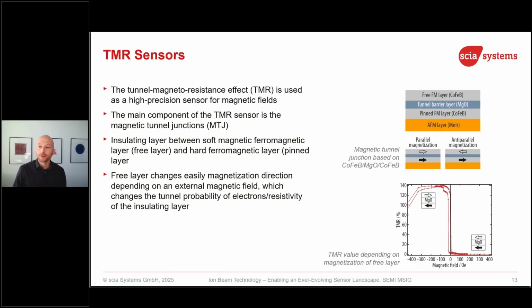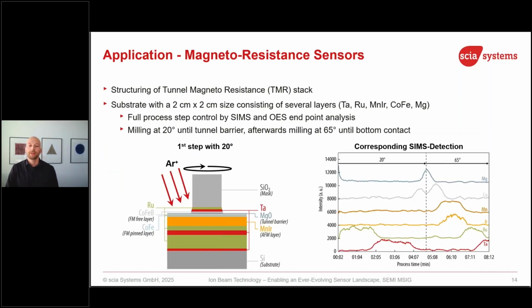So we have a lot of different materials. We have this oxide layer, we have magnetic materials, and even more. Now we have to make such a sensor. Difficult, right? First, of course, one has to deposit all those materials, and here we see a principle sketch of that sensor with the different materials. First we have a mask on top. In that case, it's silicon dioxide, but it could also be photoresist, for example. Then we have some metals, ruthenium, tantalum, and some magnetic materials. Magnesium oxide is the tunnel barrier, and also the antiferromagnetic layer, manganese-iridium.